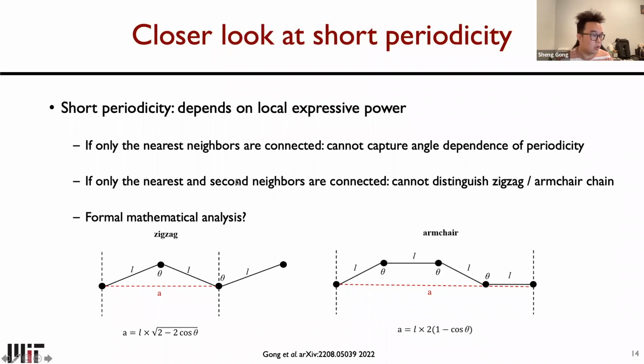And if we slightly increase the power of GNN, which is to connect the nearest and the second nearest neighbors, then we can imagine that the angle dependence can be captured because the length of the triangle is known to the GNN now. But this slightly increased power graph neural network cannot distinguish the zigzag and armchair chains with the same bond length and the same bond angle. Therefore, this graph neural network cannot fully resolve the problem of capturing periodicity of zigzag chains and armchair chains. So as a person from the materials discipline, this is what I can do to illustrate this problem.